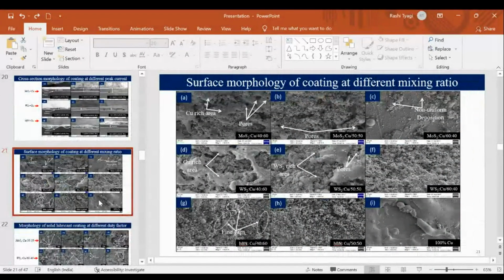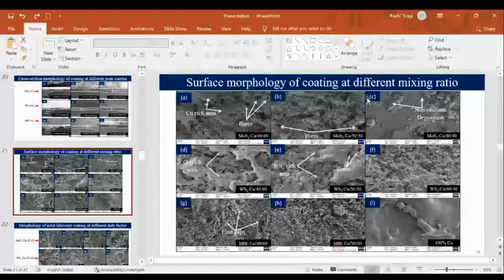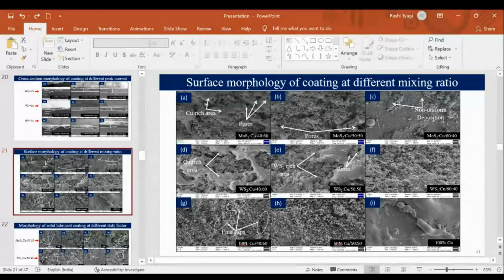So this is the surface morphology of the coating at different mixing ratios. Figures A to C show the MoS2 to copper ratio. The MoS2 to copper ratio changes from 40:60 to 60:40. It means when MoS2 is 40% and copper is 60%. In this, MoS2 is 60 and copper is 40. Similarly, this is 50:50 MoS2 and copper. So we observed the change.